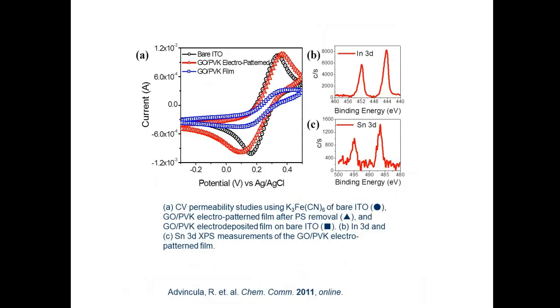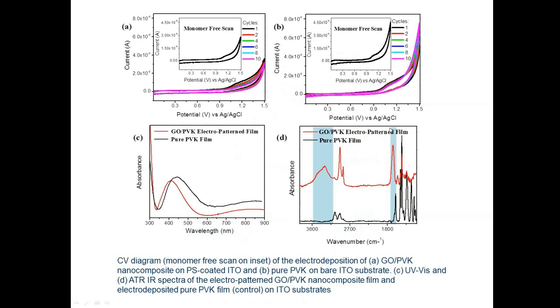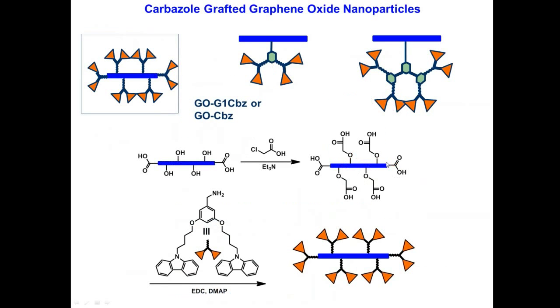This has potential for use as membrane materials that are electrochemically tuned. The XPS, or X-ray photoelectron spectroscopy, results shown here confirm the ITO substrate can be observed because of the presence of holes during the templating process.